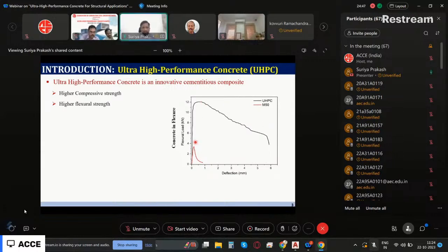Now this is very, very important. This is in flexure. So I take a small concrete prism and then I subject it to 4-point load. If I plot this load versus deflection curve, here again I have two curves. One is the red color one, another one is the black color. The black is the UHPC and red color is the M50. So you see here M50 at even a load of about 3.5 or so, it is cracking and failing suddenly. But if you look at UHPC, just as a typical example, this also I can increase it. This is in load, not in megapascal. So 3.5 has become almost 12. So it can take very high amounts of flexural load.